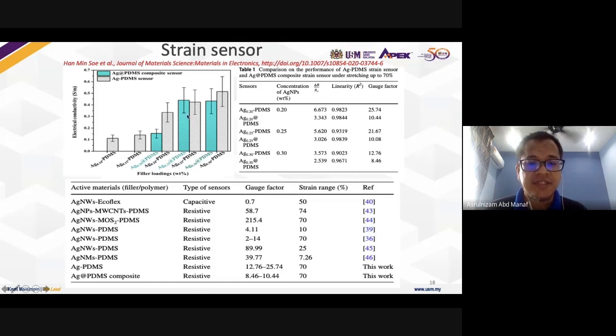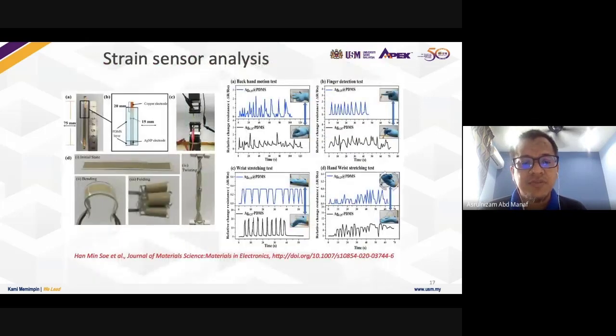With that structure we got good gauge factors, and the strain range can be up to 70%. But the latest stretchability, I think last week we had a keynote talk from a professor, goes up to 1,000 percent stretchability. That is very good, and we only have 70%. Of course you need to play around with the material properties. This is what we tested.